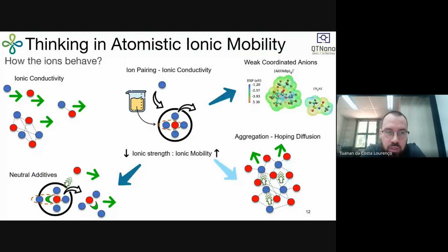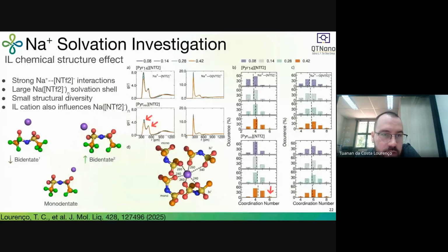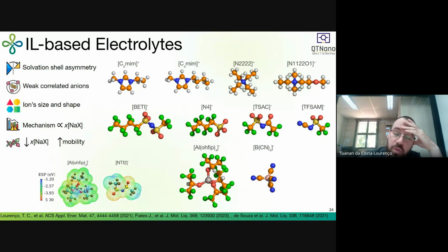You mean how the entropy behavior could impact the... Exactly. So I have an extra slide here. In general, when you have a cation and an anion interacting, it's always good to have an asymmetric ion, like this anion here. Since this is asymmetrical, the solvation shell that we are going to see in the electrolyte will also be asymmetrical. So somehow we can say that if we use asymmetry in the ions, we have a higher entropic behavior in the system.